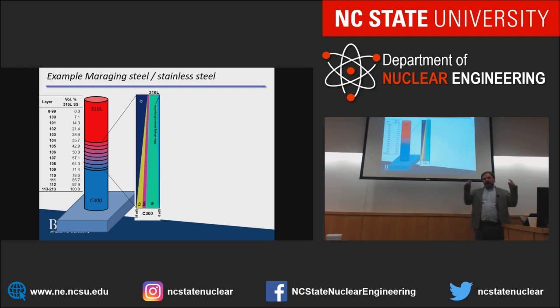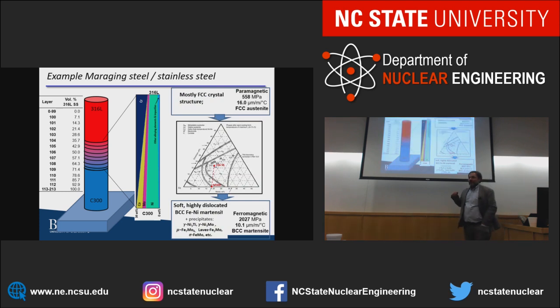Change the composition by each layer, gets a different powder composition. Turns out that's easier said than done, because you do have to consider phase diagrams to make sure that you're not hitting some weird phases in between. Now, fortunately, there's not too many bad things going on between maraging steel and 316. But you do have to consider that these maraging steels form a lot of intermetallic precipitates. Stainless steel doesn't. Stainless steel is paramagnetic. This one is ferromagnetic. And the strength is 4 times different. And of course, the thermal expansion is different too. So there's a risk of one ripping the other one apart.